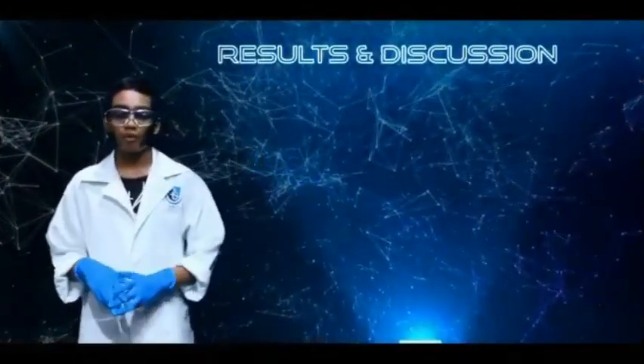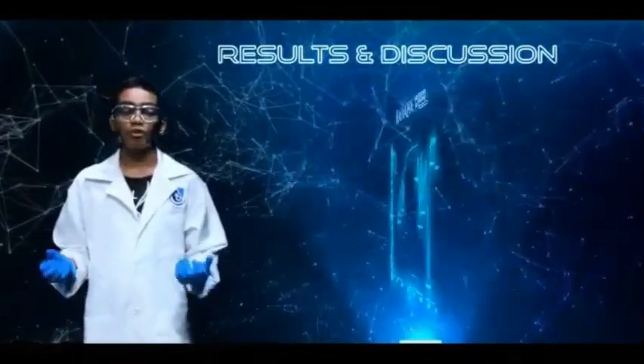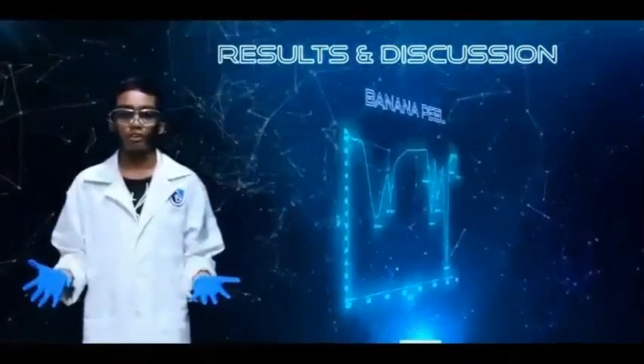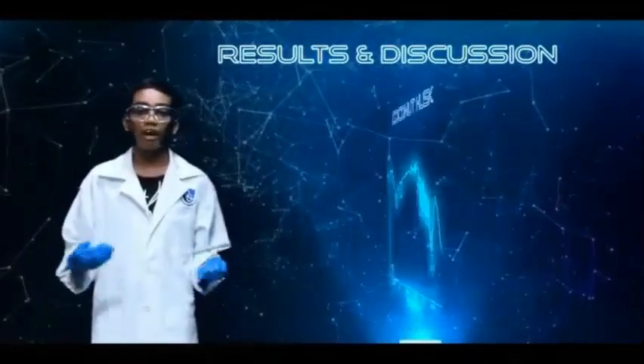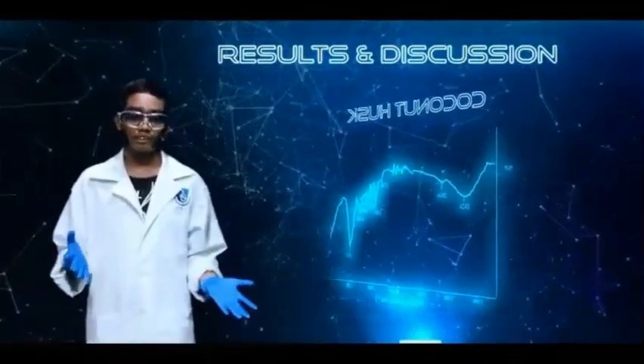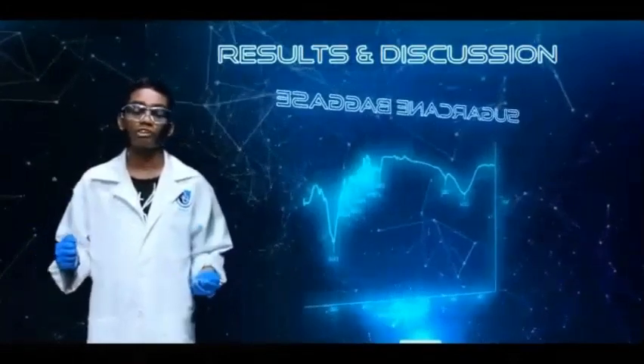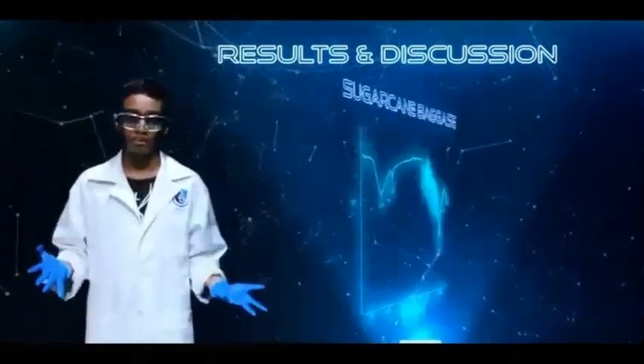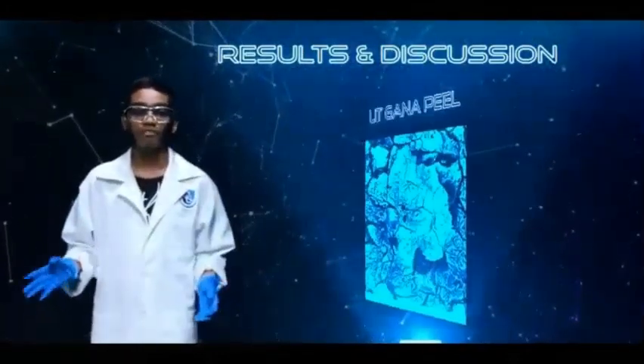Results and Discussion. Based on our FTIR analysis, we found that banana peel has more functional groups than sugarcane bagasse and coconut husk. In SEM analysis, it revealed that banana peel has more porous structure than sugarcane bagasse and coconut husk.